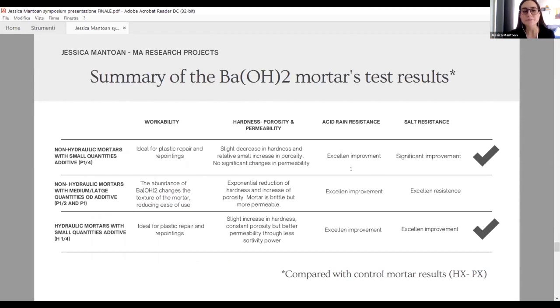About the non-hydraulic mortar containing medium and large quantity of barium hydroxide, even if overall the results were not too negative, they cannot be considered acceptable for any conservation treatment, because in particular regarding the porosity and the hardness, the change from the traditional mortar is too different, and the material is considered too weak to be used in real conservation treatment.